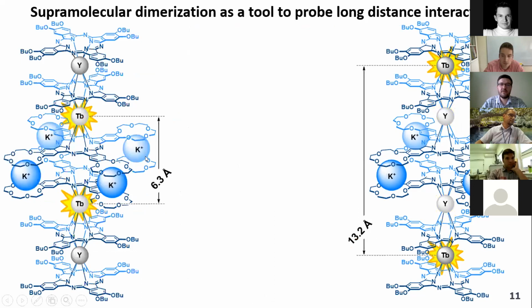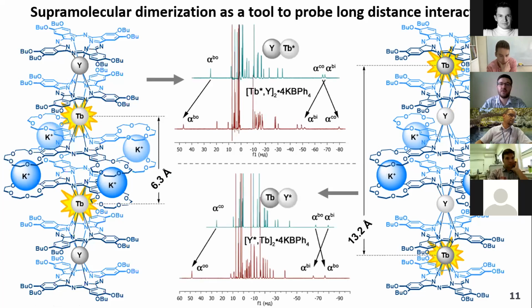So these objects are also interesting from the viewpoint of studying long-range molecular interactions. For example, we can use different heteronuclear complexes to obtain dimers with separation between terbium ions ranging from 6 to 13 angstrom. By the moment, we didn't start making magnetic measurements on these complexes, but we could use NMR spectroscopy to get first insights into their magnetic properties. And we can see that invariant to arrangement of terbium ions in these dimers, invariant to distances between these metal ions, we have very strong shifts of resonance signals of protons upon the formation of supramolecular dimers.